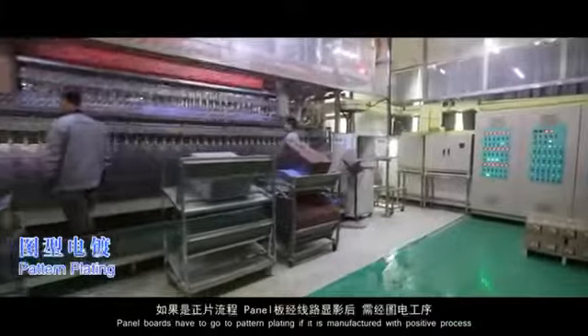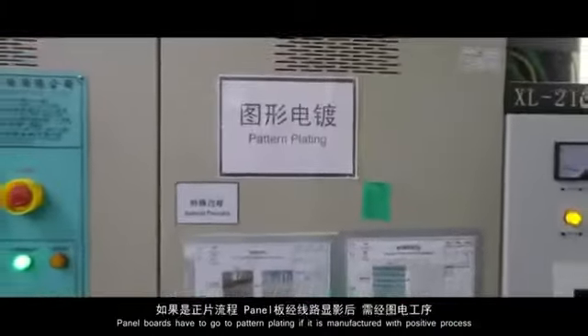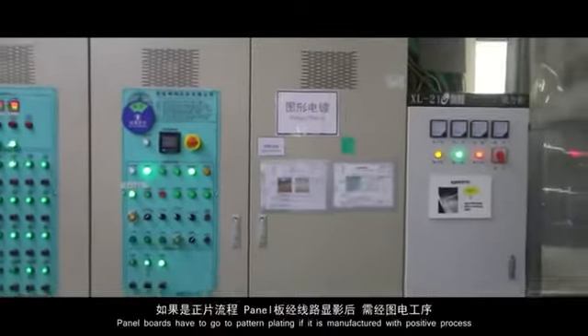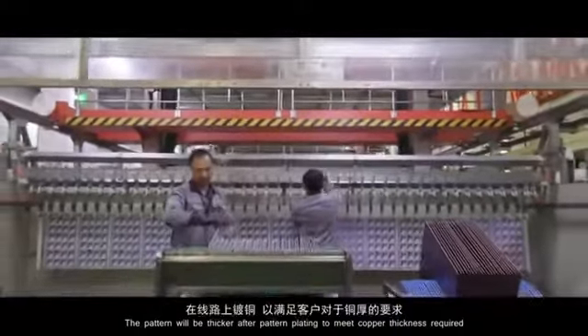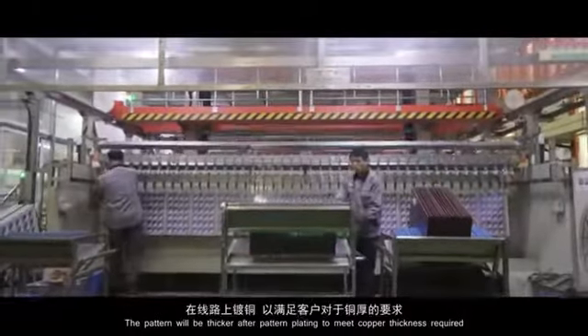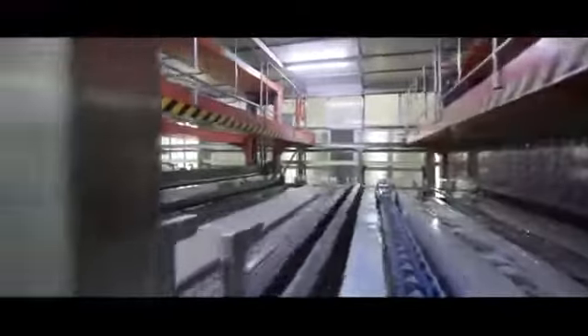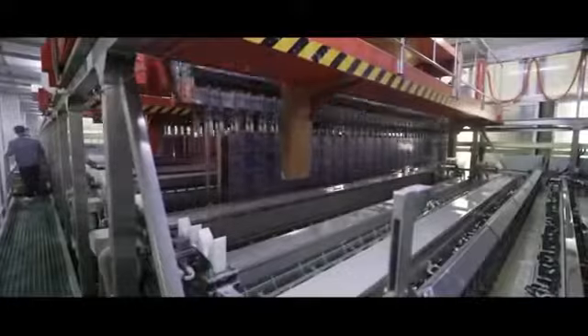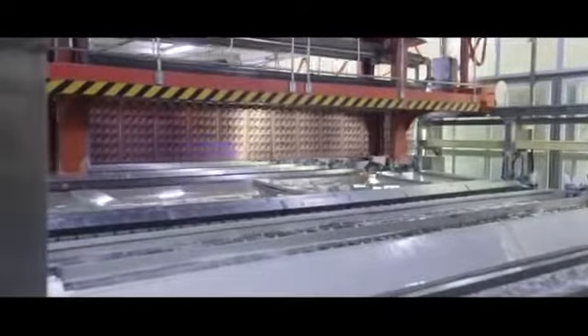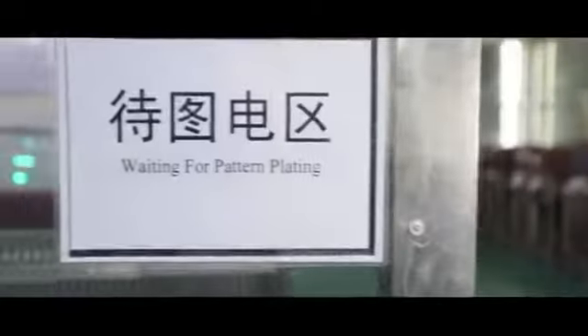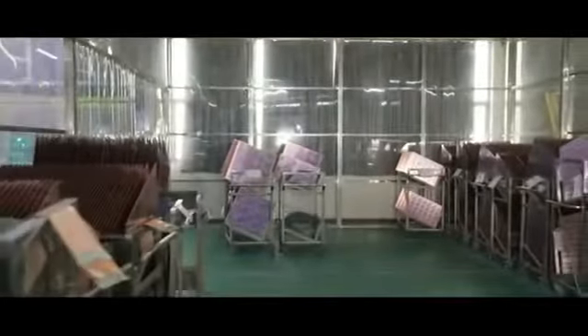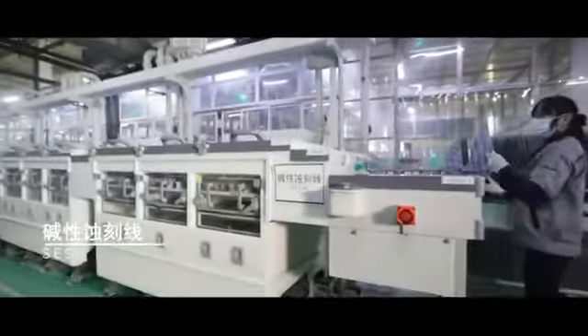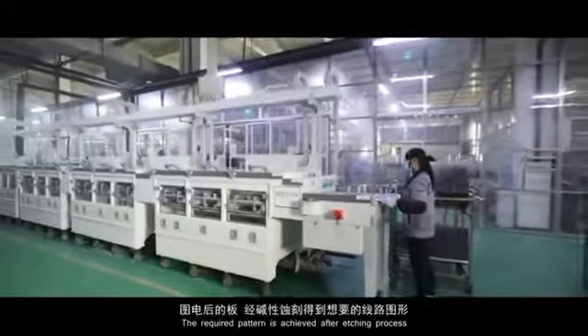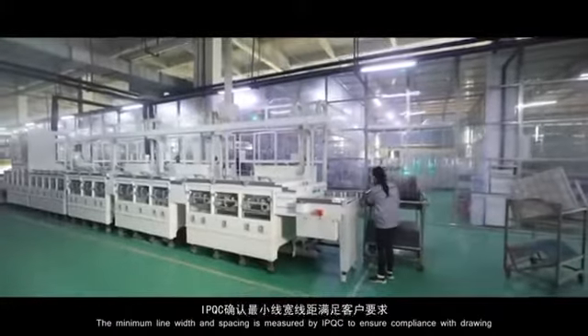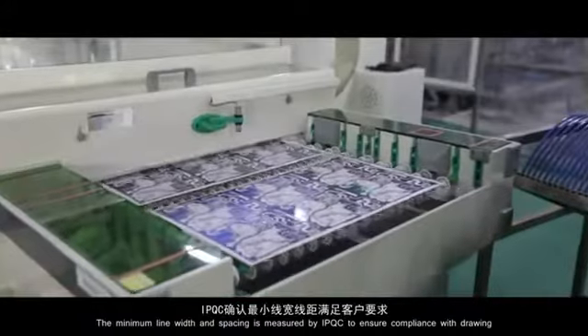Panel boards have to go to pattern plating if manufactured with a positive process. The pattern will be thicker after pattern plating to meet the copper thickness required. The required pattern is achieved after the etching process. The minimum line width and spacing is measured by IPQC to ensure compliance with the drawing.